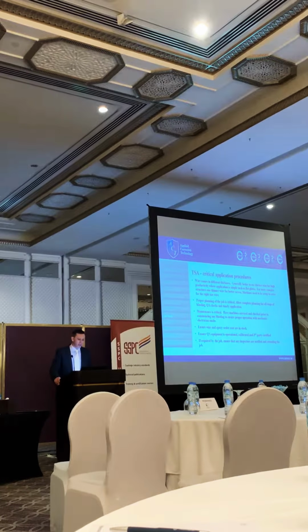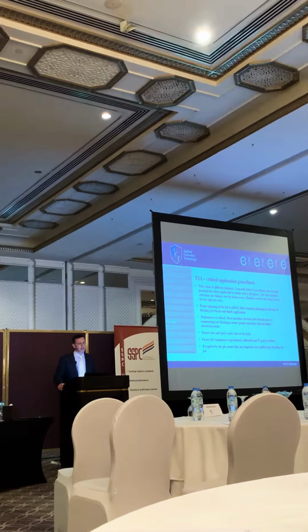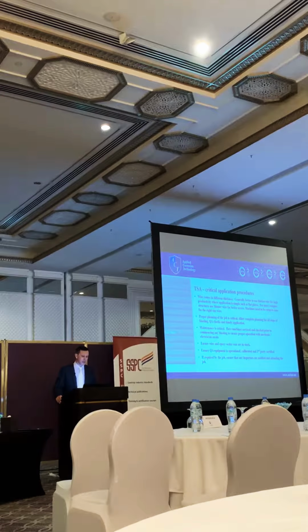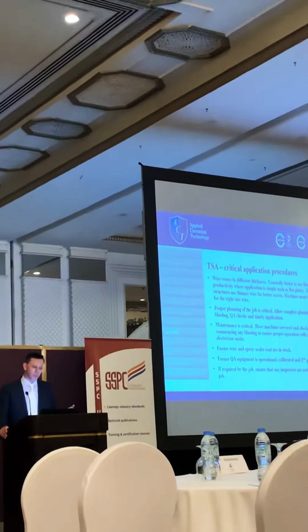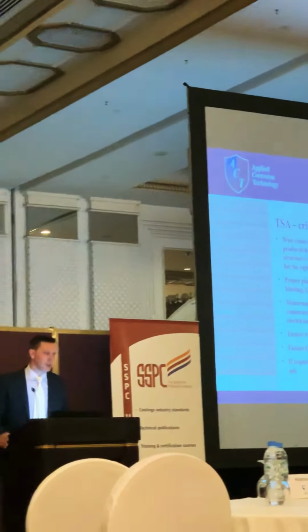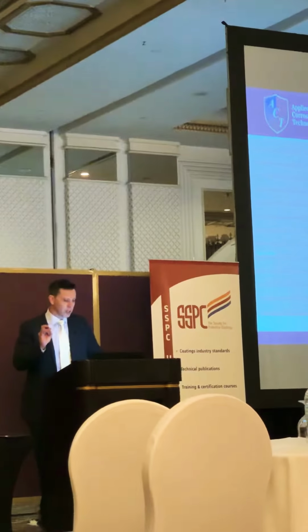There are different wires, different wire thicknesses and gauges, I should say. We find that it's generally better to use a thicker wire when we can get high productivity, where we're looking at a simple substrate, such as flat plates, and for more complex structures, we use a thinner wire where we can get better maneuverability and better control over the DFT, which again comes back to the project planning. Your machines need to be set up to cater for the correct size of wire that you want to use.